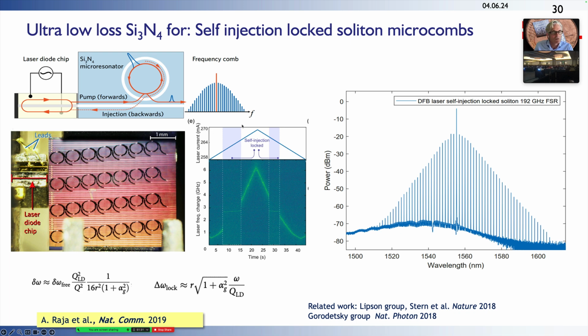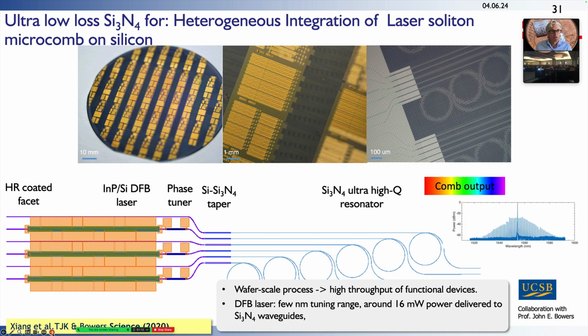But in addition, we can also generate, on top of this dynamics, a dissipative Kerr soliton. So these are very compact soliton generators, and it's this very low loss in the silicon nitride that allows us to create a threshold that's comparable to and lower than the typical DFB output. So what is the most compact optical comb we can make to date?